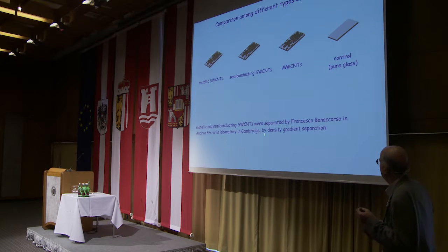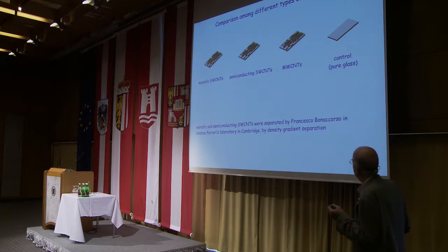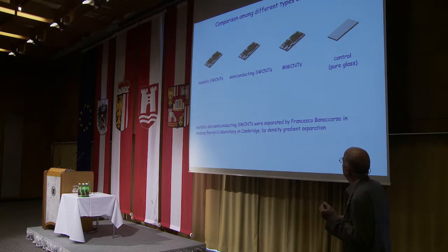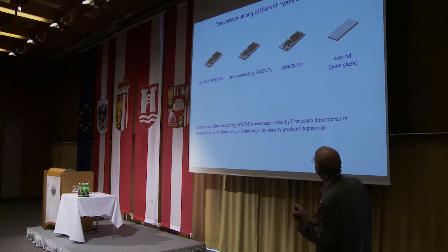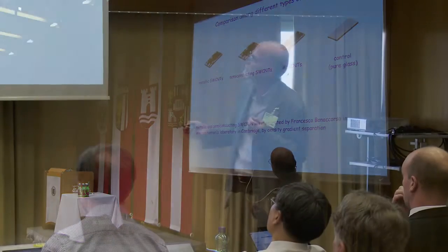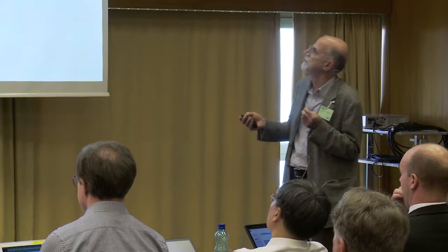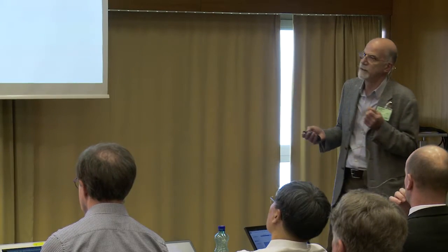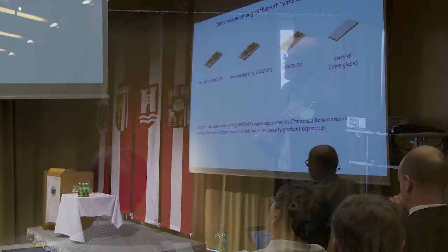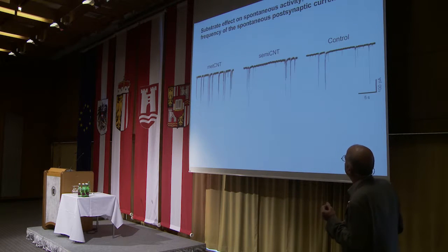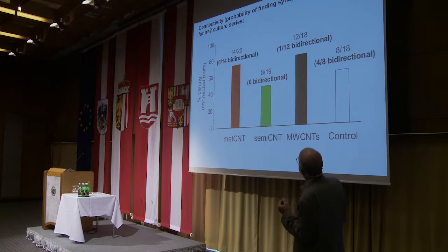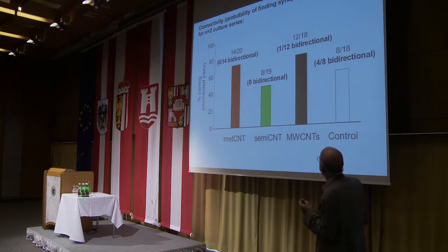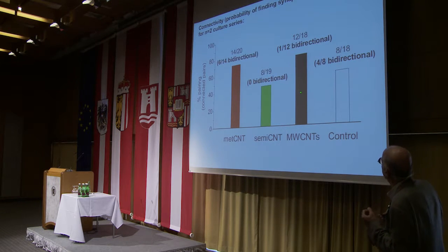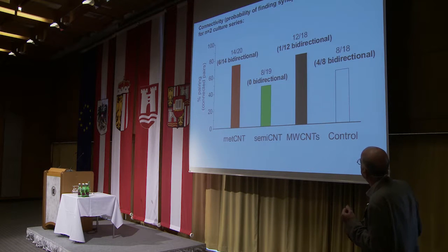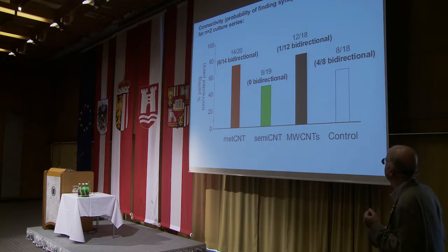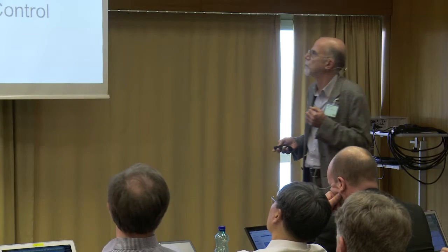So we collaborated with Andrea Ferrari in Cambridge, and they coated glasses for us using separated metallic and semiconducting carbon nanotubes, and we compared them with multi-wall carbon nanotubes and the control, which is pure glass. What we see is that only the metallic nanotubes behave like multi-wall carbon nanotubes in terms of increased number of synapses, whereas the semiconducting carbon nanotubes behave very similar to the control.